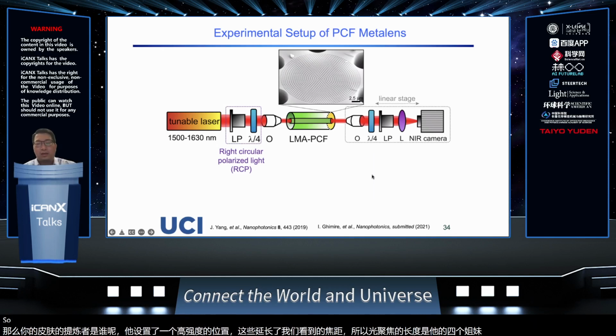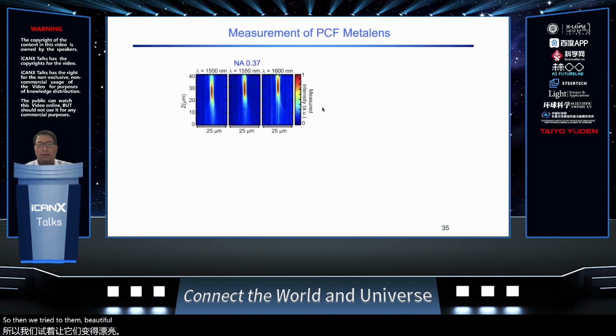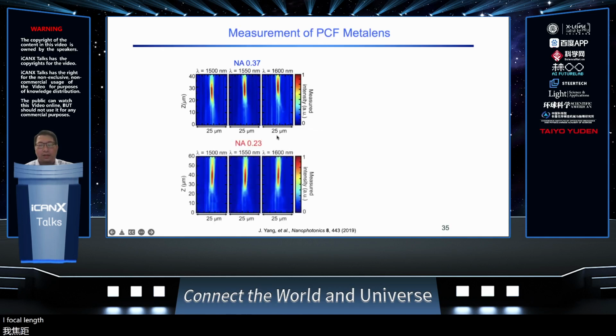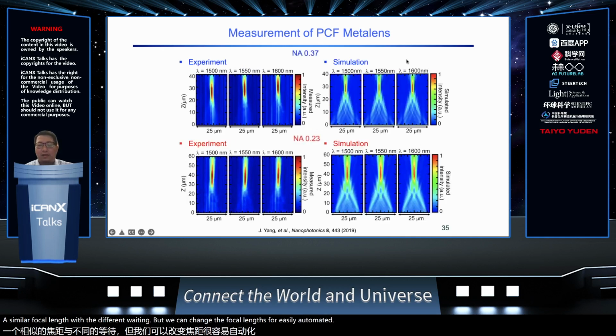Then we try to do different measurements. For example, for the fiber with this NA of lenses, you see different wavelengths. We have a focusing effect with a similar focal length. And by changing the lenses, you see we also have similar focal lengths with different wavelengths, but we can change the focal length quite easily here to 40 micron. Compared with simulation, we have a similar result in terms of the focal length and also the beam width here.